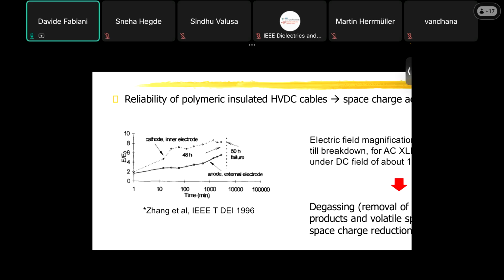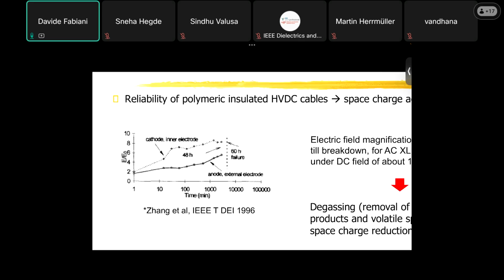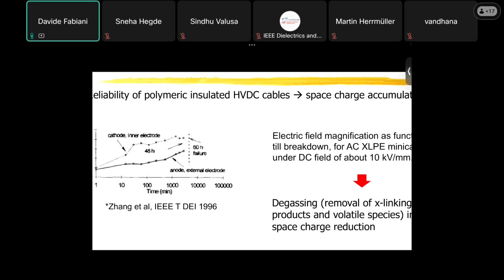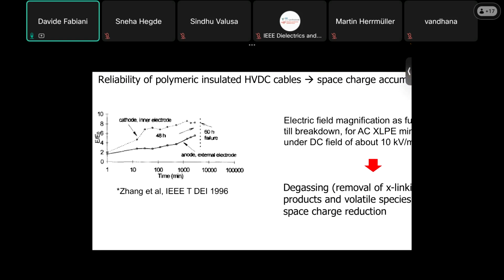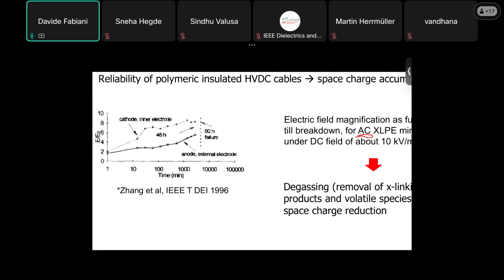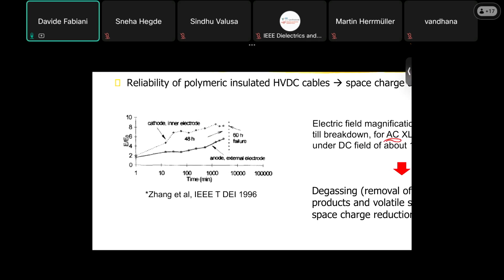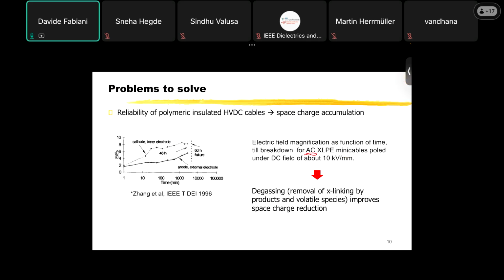In the 90s, at the end of the 90s, someone wanted to use the XLPE material that was used for AC applications for DC application. And the problem was that the AC cable fed under DC, even at low electric field, let's say not very high electric field, let's say 10 kilovolt per millimeter, after a few tens of hours of service, as you can see here, 60 hours, the cable failed.